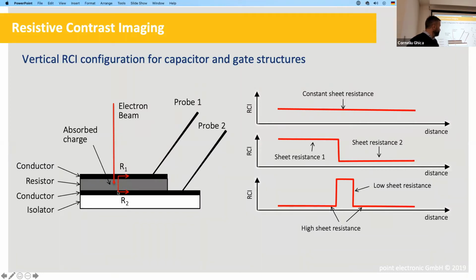And we want to find out at which points along this oxide there is a weakness, so the oxide is not as isolating as it should be, so there's a leakage path of some sort. If the material is perfect, then we should see a constant signal, so maybe some variations, as sometimes the oxide is not perfectly uniform in thickness and quality and so on. If there are two regions in this oxide, say very different capacitance or very different resistance or leakage across, then we would have quite a sharp transition. And if there is a leakage site, a position on the device where there is a high leakage current, then it will show us a spot.